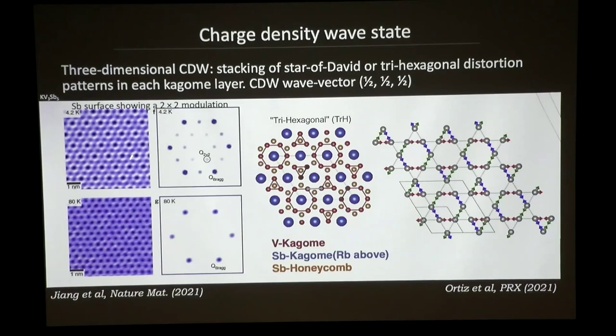When you cool down to low temperatures, you enter the CDW phase. You can see these two images look different by eye. And when you take the Fourier transform, you see extra peaks. And these 6 extra peaks represent the charge density wave peaks. So in this compound, you have an additional periodicity that happens at low temperatures, which is twice the atomic periodicity in 3 different directions.